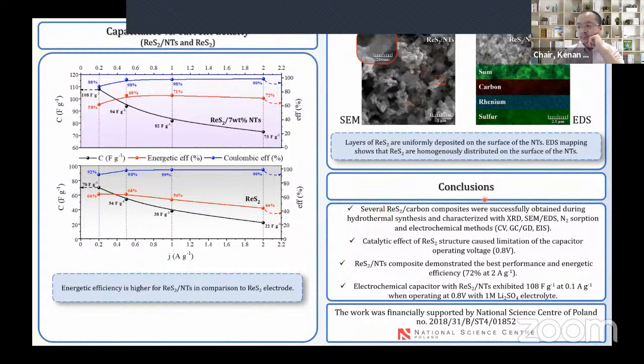And just to summarize this work, we have prepared several carbon ReS2 materials, and it occurs that the best performance was reached for the rhenium disulfide deposited on the nanotubes. Sadly, the catalytic effect of the ReS2 structure caused limitation of the capacitor operating voltage up to 0.8 volt.